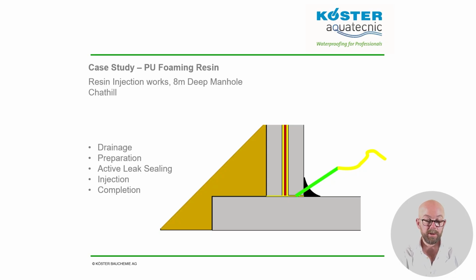During injection of the first position, a close eye was kept on the other 3 hoses. When resin entered through another hose, the first hose was then crimped and injection switched to the one the resin was coming out of. In this way, a continuity of injection was achieved all round the base. Once all the easiest pathways were sealed off, the expanding foam resin was pushed out through the original leak routes into the soil surrounding the base.